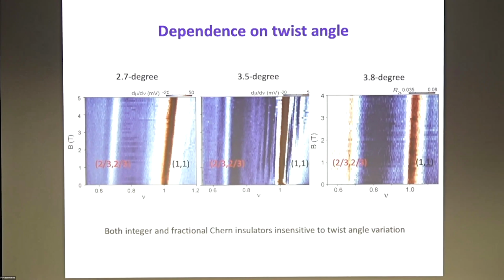Yeah. I guess the probing area is about the diffraction limited area, about a micron. How homogeneous is that sample as you change the location? So if you ask me about a transport device that we make, because we pick only those that are uniform within about 5 micron by 2 micron area, it's pretty homogeneous in order to do the transport. In this kind of device, we did not try to pick those that have a large area homogeneity, because we can just measure locally and you can easily see angle variation.